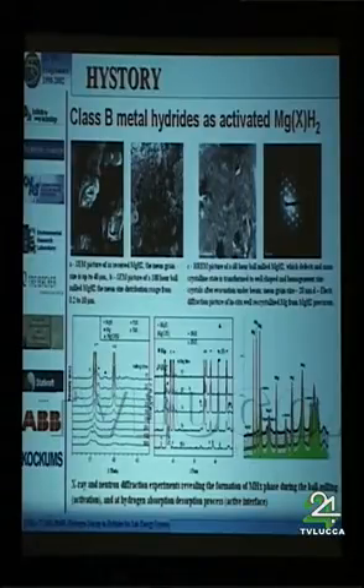Also, we have considered that the catalyst acts actively on the kinetics. For example, when we ball mill magnesium with titanium or with niobium or with vanadium, we saw when we look at different ball milling times that first the catalyst is hydrogenated progressively, for all the materials we use. And also when we have performed in situ neutron diffraction experiments, for example, starting from fully desorbed materials, we can evidence and confirm what has been shown first by Jacques Huot on magnesium, that first the catalyst takes up hydrogen, and after only magnesium hydride is formed.